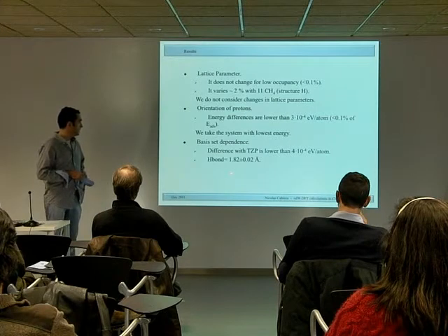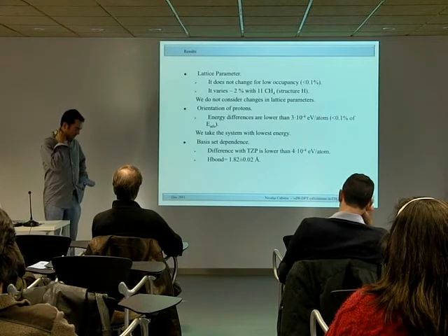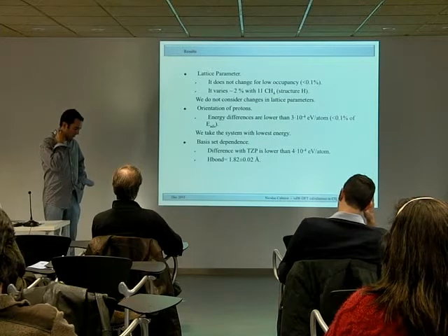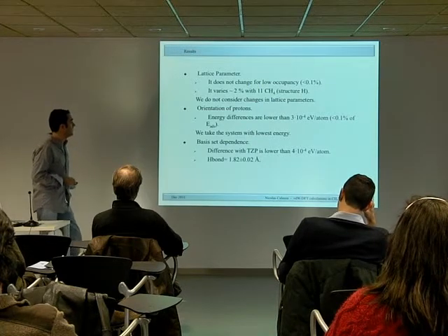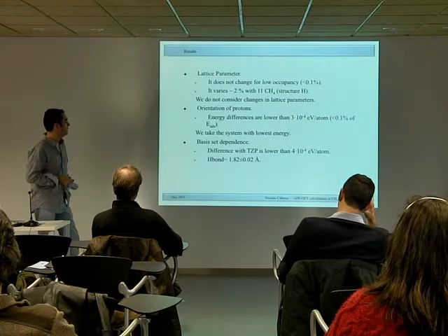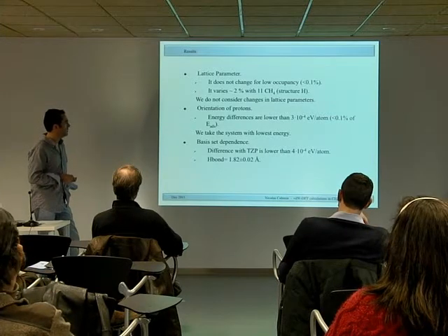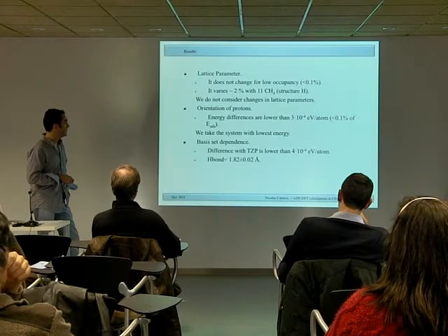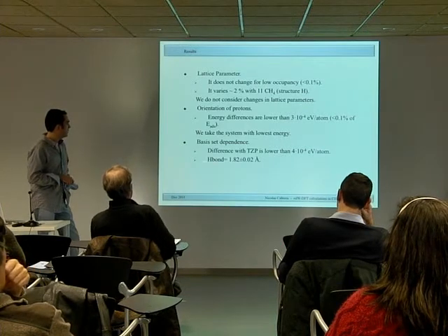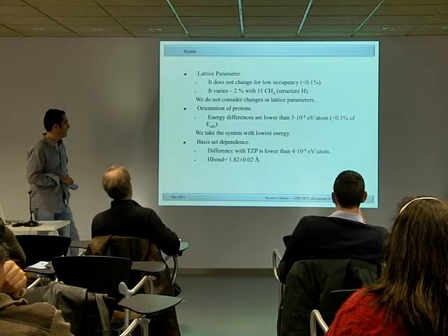We use double zeta polarized optimized basis sets for the system, but in order to check that the basis was complete enough, we did some calculations with triple zeta polarized. Again, we see that the differences in energy are very small, and for example, we checked that the H-bond lengths are exactly the same.